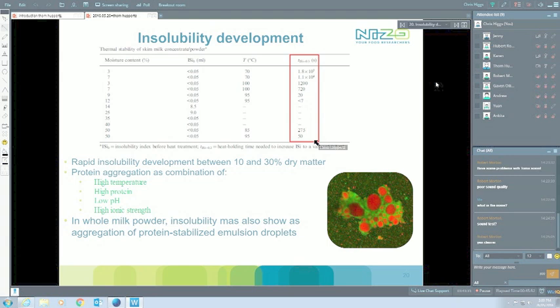It's really in that intermediate stage, when you start taking out a bit more water, that you get into that range of 10 to 30% moisture. I see it says dry matter on the slide there, it should say 10 to 30% moisture. That's where the rapid insolubility will start creating. It's that point where you've taken a good bit of water out, but there's still quite a bit left. There's enough mobility there still for the proteins to aggregate, to destabilize.